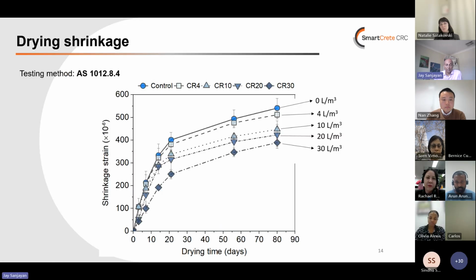And drying shrinkage is another big issue often in concrete. And we can see a beneficial effect from 0 to 4 liters, 10 liters, 20 liters, 30 liters. We measured shrinkage up to 70, 80 days, but normally it's only required up to 56 days. So you can look at the 56-day results.